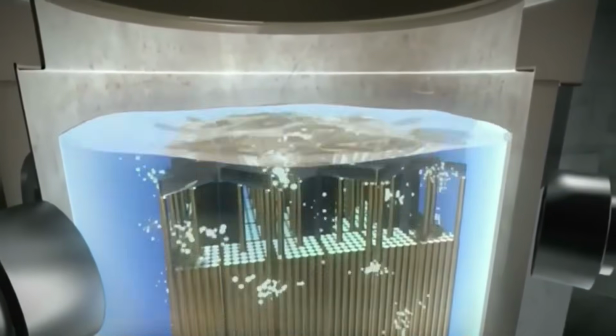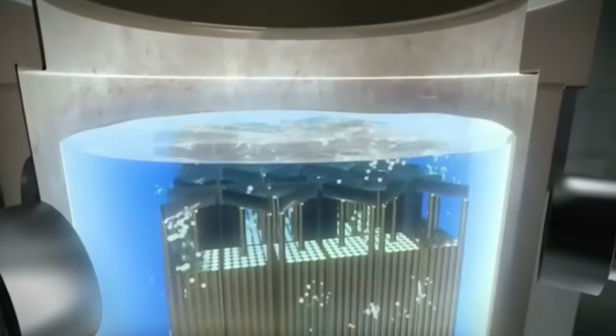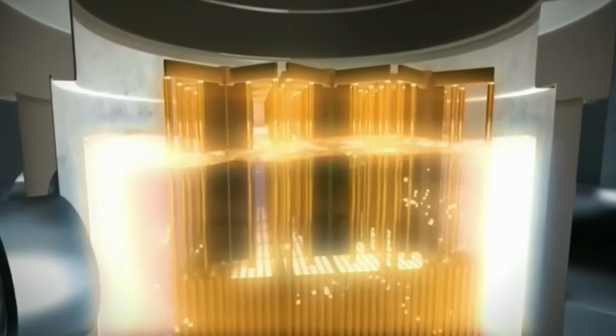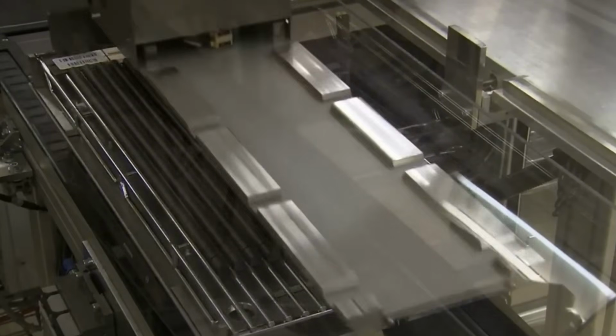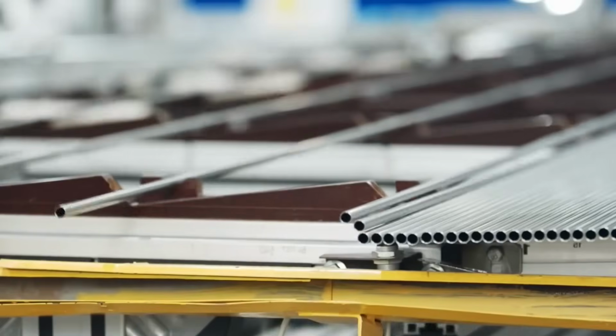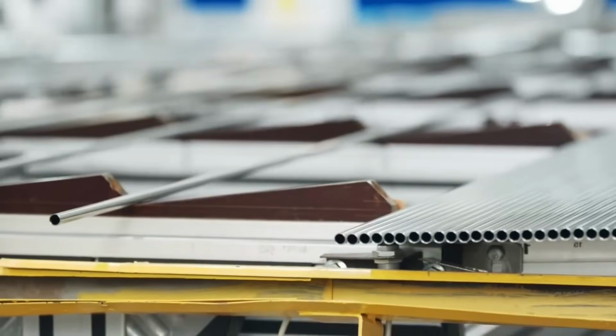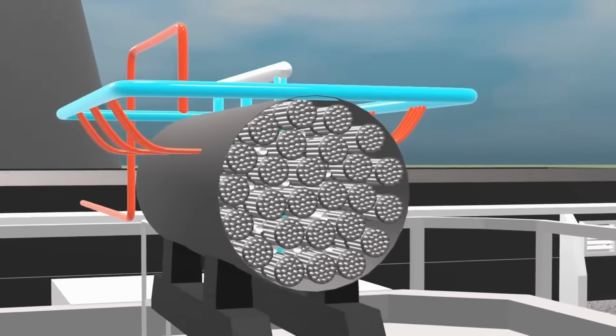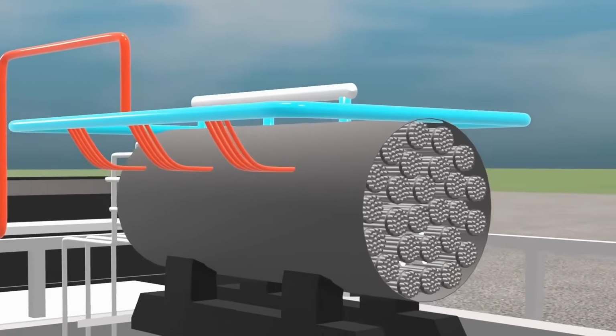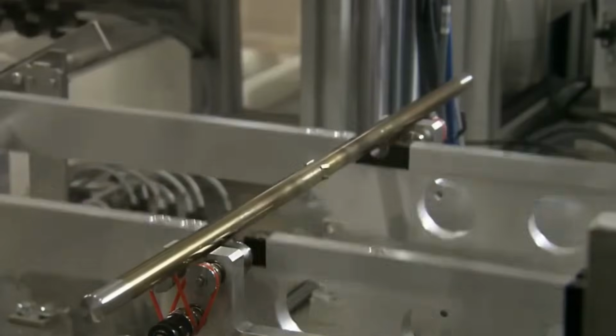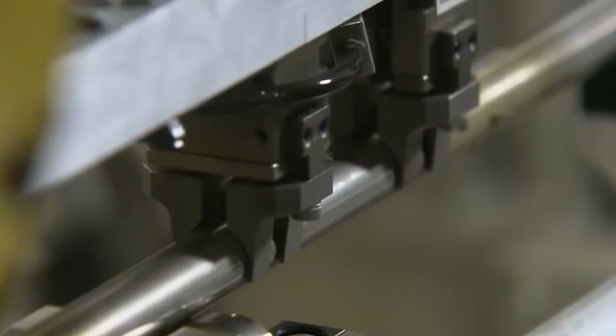The loading of the pellets into those tubes is carried out under very careful conditions. The ceramic column must remain correctly distributed and aligned. In some designs, auxiliary internal components are incorporated to help maintain mechanical stability during operation. Once the loading is completed, the ends of the tube are sealed using high-precision welds. Hermeticity is essential. A fuel rod needs to preserve structural integrity and containment throughout its entire cycle of use. When the tube is sealed, it becomes a fuel rod.